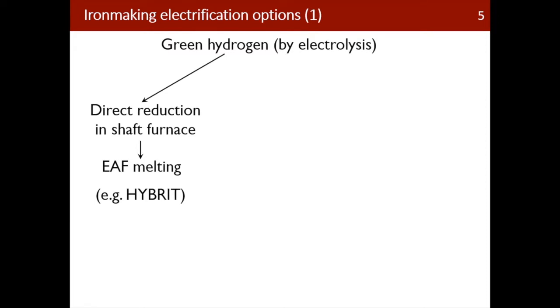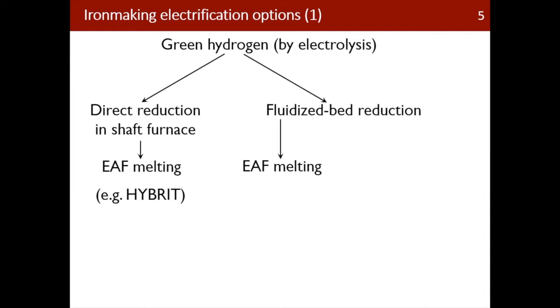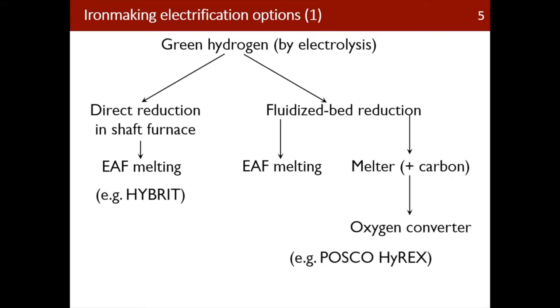There are some detailed things around, you know, the mechanical strength of the product here and some loss in melting, and of course, current arc furnace operations really need carbon for the quality of the product, but those are, I think, engineering issues that we shall be able to solve. The alternative is what is being developed by POSCO, which is use a smaller size feed material, reduce that in a fluidized bed, again, melt it in an electric arc furnace, or first melt it with some carbon, and then convert that in a traditional oxygen converter, which has some quality advantages potentially. So again, these really rely on largely proven technology. So it basically can work, and there are various plants under construction to demonstrate that that's indeed the case.